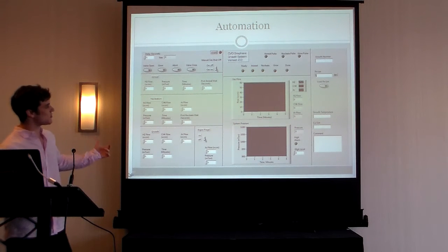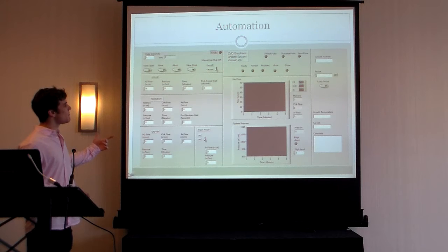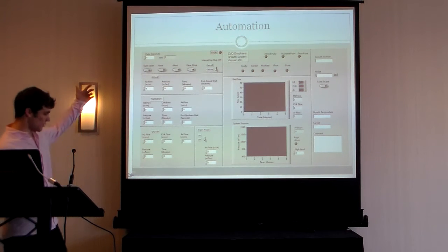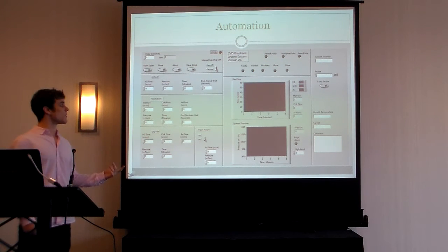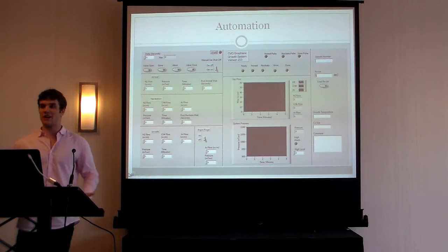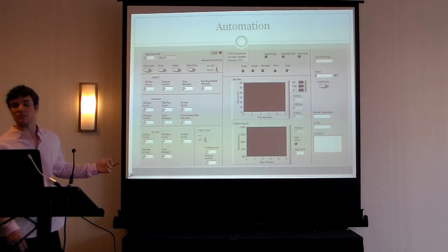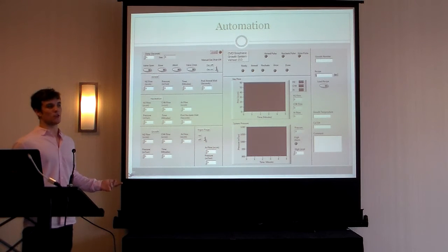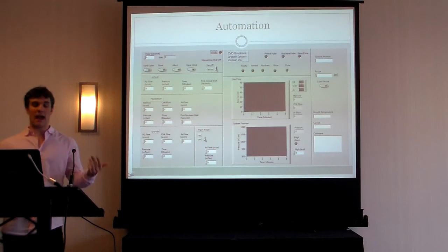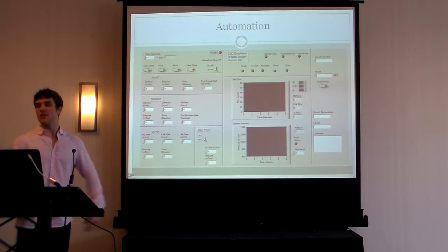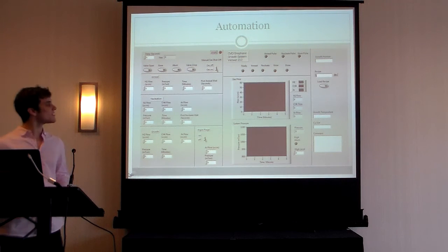And these recipes can actually be loaded back into the program from the log file, so that you can have a very repeatable system. So you can say, oh, look, there was a pressure spike at 3 minutes into growth, and then your samples have some abnormality. You can understand why that's happening, or at least have a better guess.